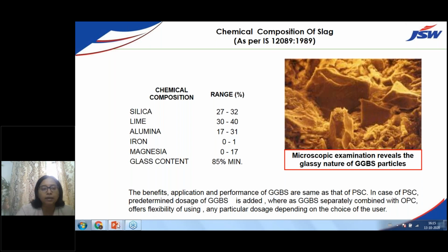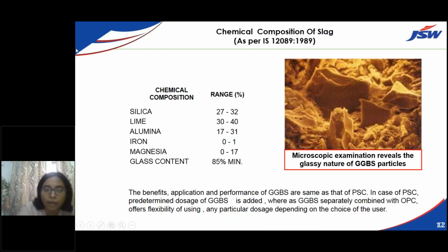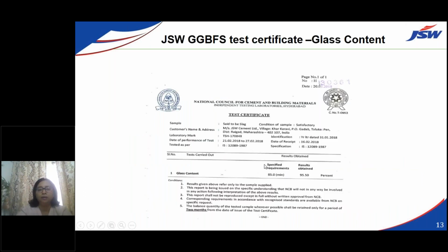With the help of this glass content, the product which we will be making will be very reactive, and the particles of slag will be so good. It is not only going to give you strength from the calcium oxide, the lime content at 30 to 40%, but it will also give you the durability you require, and added benefits like workability of the mix. We are showing you some microscopic examination of the glassy nature of GGBS particles. We are also enclosing some test certificates. You can see here our glass content goes up to 97%. In many cases, the test certificate done at NCCBM shows 95.5% glass content.